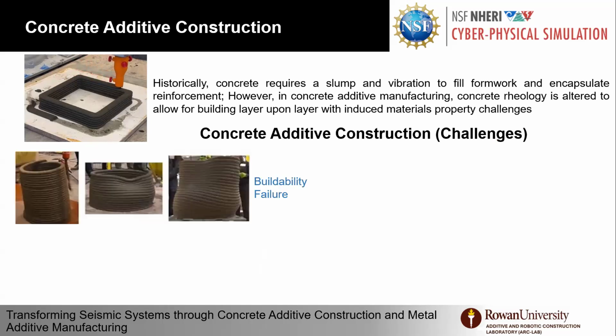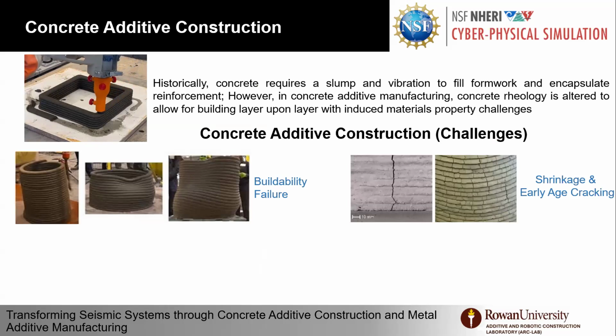But there are a lot of challenges in this process. The first one, you will be able to get some collapses and learn from the collapses. The material is fresh, gaining strength over time, so there are buildability failures. There are also shrinkage problems, cracks due to shrinkage, and also early age cracking. Now we think about having the entire structure or element exposed to the ambient condition. It's not in formwork anymore, so the shrinkage problem is different.